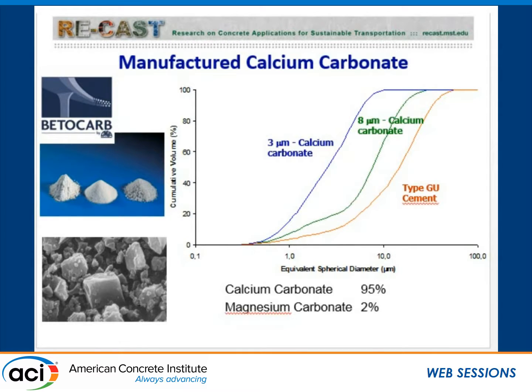We used a number of different limestone fillers. Here you have the grain size distribution. This is your typical type 1 Portland cement. In Canada, we call it general use. And then you have one of the Betocarbs. So they had them at different grain size distribution. We tried the 20 and the 13, and here I'm showing the 8 and the 3. And the 8 and the 3 refer to the D50.